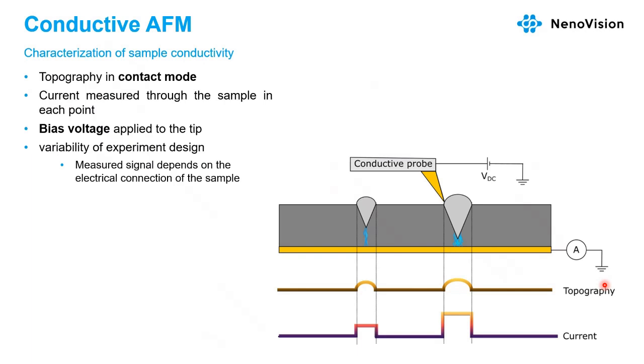So conductive AFM analysis of the sample surface is measured using topography in the contact mode. And at the same time, we are measuring current through the sample in each point of the map. So there is variability in the experimental designs. In our case, we apply bias voltage to the tip, and simply we measure where the sample is more or less conductive.